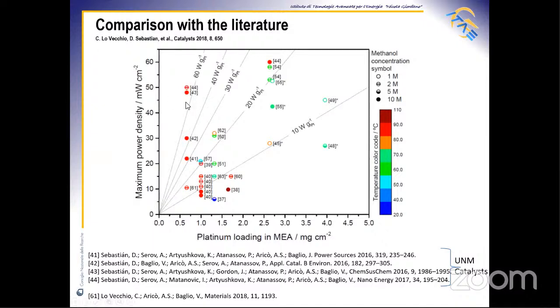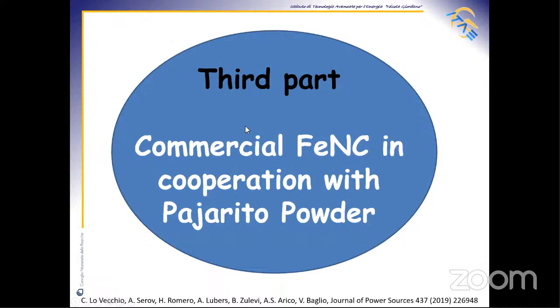Performances larger than 60 watt per gram of platinum can be reached even with the high methanol concentration of 10 molar, thanks to their extraordinary tolerance to methanol. This means that it is preferred to employ the most expensive metal, platinum, only at the anode, in order to take advantage of the methanol tolerant properties of MNC catalyst at the cathode and to design systems with prolonged operation in high methanol concentration. In the third and final part, we will talk about the commercial FeNC in cooperation with Pajarito Powder.